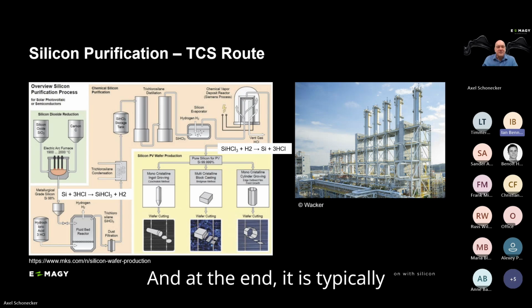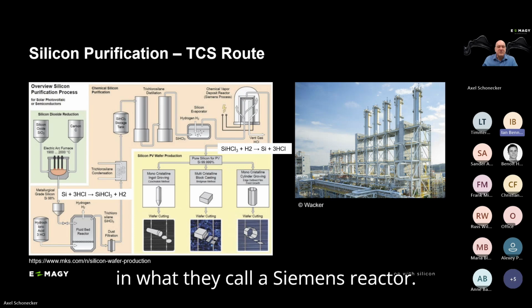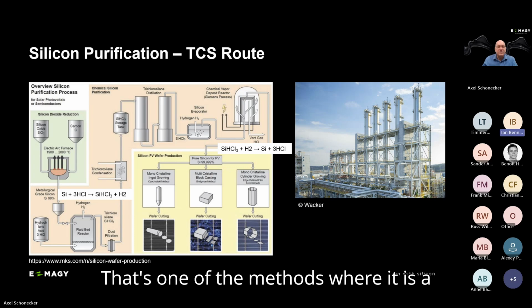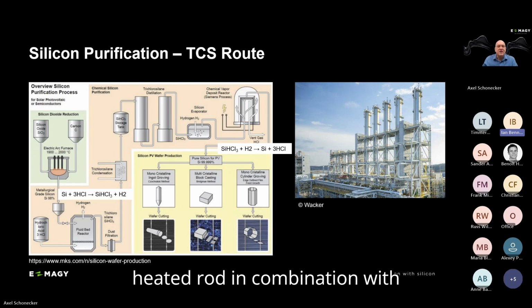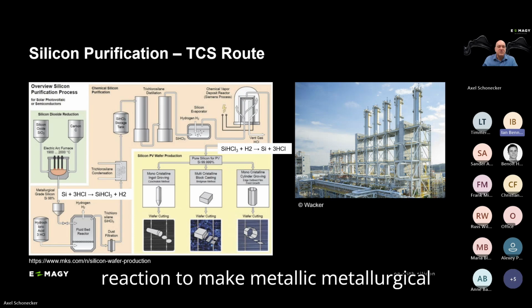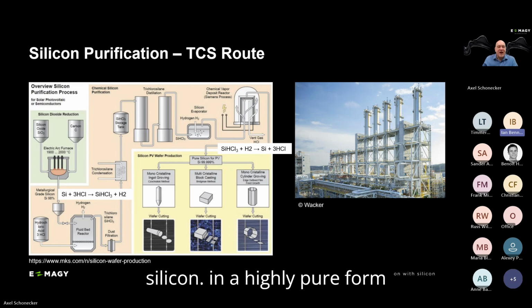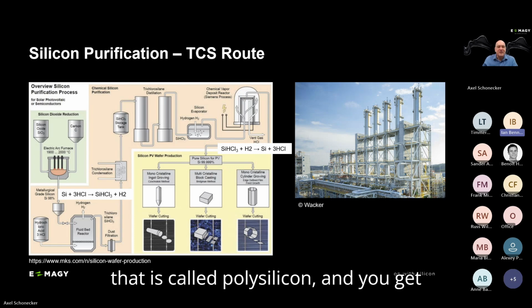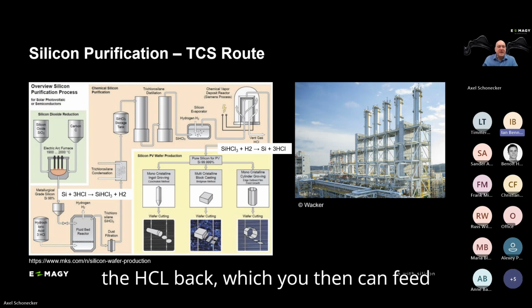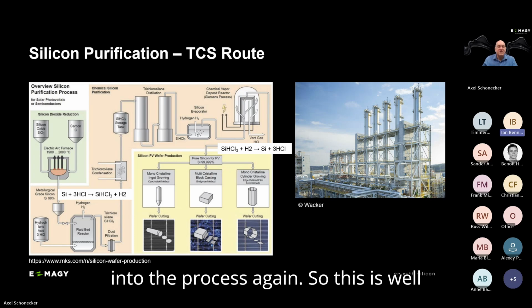And at the end, it is typically reduced into metallic silicon in what they call a Siemens reactor. That's one of the methods where a heated rod in combination with hydrogen leads to the reaction to make silicon in a highly pure form that is called polysilicon, and you get the HCl back, which you then can feed into the process again.